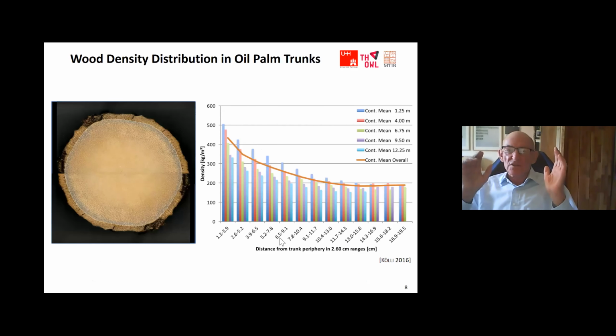So the next slide shows us one example. On the left, you see a disc from an oil palm trunk. You see the very dark color in the outer part, the high density, mainly caused by thicker cell walls and by more vascular bundles. Vascular bundles are fibers which have a high density, up to 1.4. So as the number of vascular bundles increases, the density increases, and the strength properties increase. And the diagram shows us the development of the density along the diameter of a palm trunk, with about 500 kilograms per cubic meter in the outer side and about 200 kilograms in the inner part. So this is a challenge for processing. This is a challenge for product development.